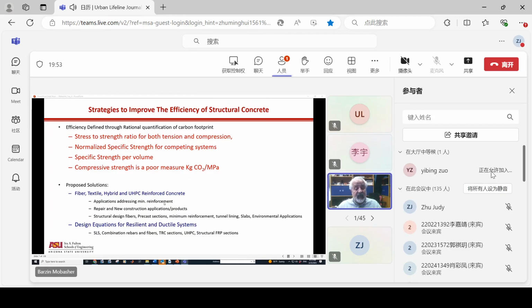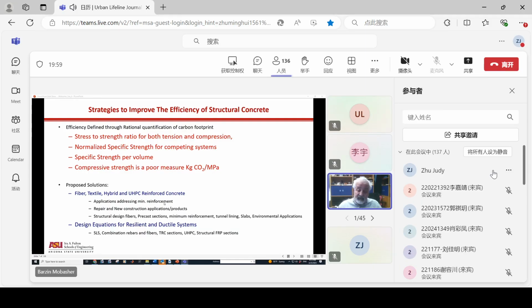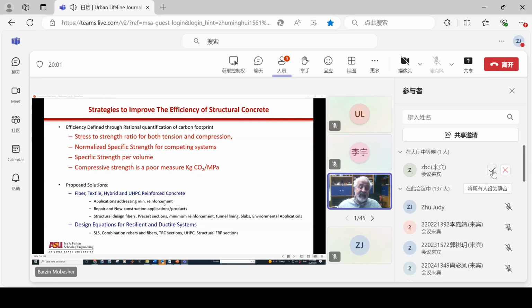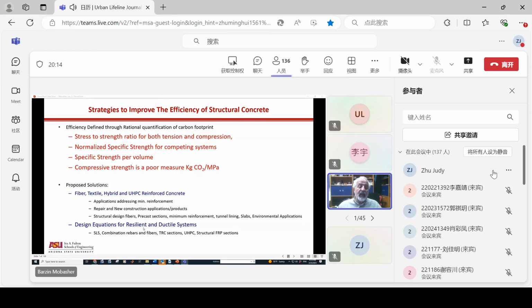Now we can make steel fibers which have about 3 times higher yield strength or even stiffness. So we can make steel much more amenable for reinforcing concrete on a kilogram per kilogram basis. The next step, which I want to get your attention, is that we should look at the way we design it. So can we develop design equations based on resilient and also ductile type systems for all of these materials?